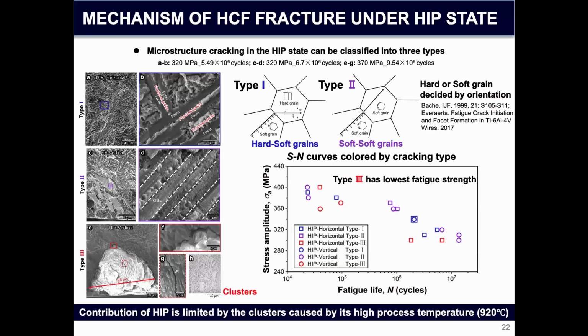And for the HIP states, there are no defects. The cracks initiate in some microstructures, and the cracking mode can be further divided into 3 types. The first type is called hard-soft grains, and the other one is called soft-soft grains. And the worst one is type 3, because this is due to the cluster of this phase. So the contribution of HIP is limited by the cluster caused by the very high temperature. We can see the symbols here for type 3. It always has the lowest strength.